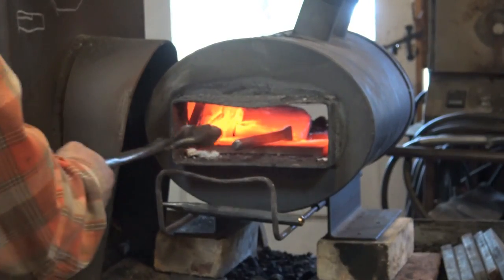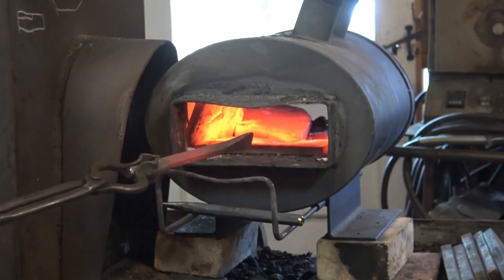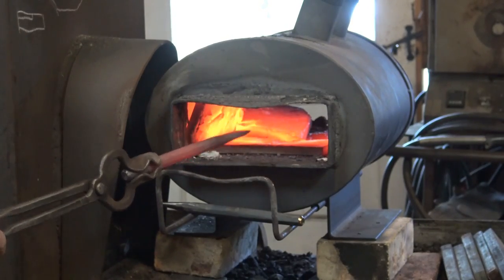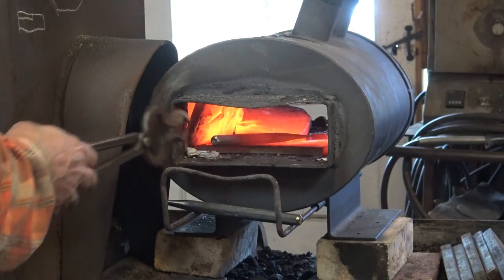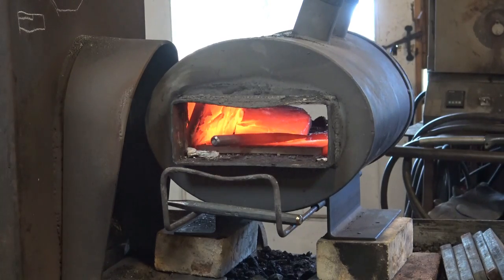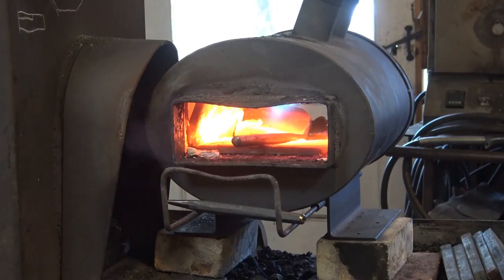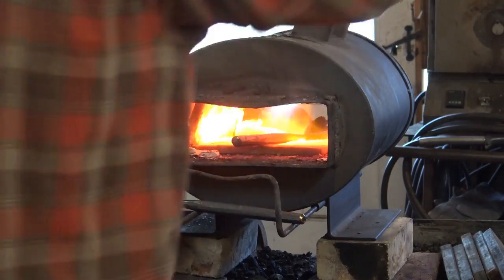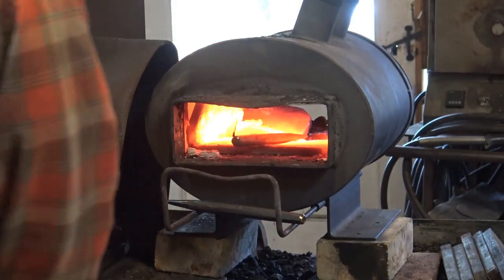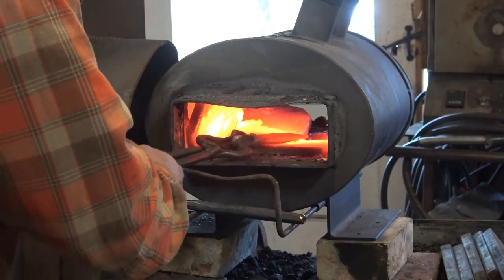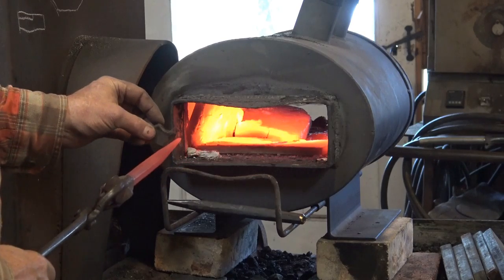While these come up to temperature, I'm going to turn the forge off a little bit for a little while here and let them soak. I want them to come up to temperature as slowly as I possibly can to make sure it's evenly hot all the way through. It's possible to have a hot outside and still have the core of the tool cold. If you do that, you're liable to crack it. Well, perhaps cold is not the right word. Not fully up to temperature.